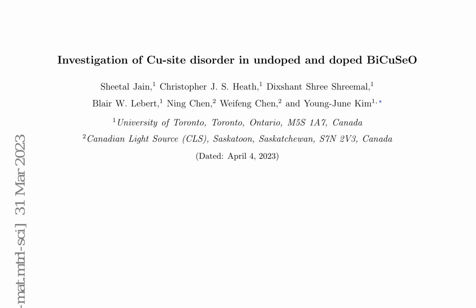Temperature-dependent extended X-ray absorption fine structure (EXAFS) measurements for Cu K-edge in undoped BiCuSeO, Ag-doped BiCuSeO, and Pb, Ag dual-doped BiCuSeO samples were analyzed to provide a direct comparison between Ag and Cu using the same EXAFS technique. The results, summarized in Table 3, present mean square displacement values for the first two shells, Cu-Se and Cu-Cu, as a function of temperature.